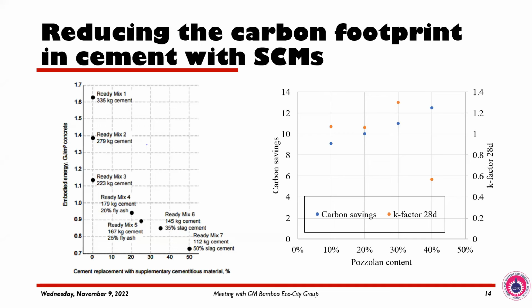So what you do is that you have a score of 1, and then you are replacing the material. If you calculate the efficiency factor of the material you are replacing, and it is below 1, then it means you can't replace cement with the material. But if you replace cement and you have an efficiency factor of above 1, then it means that, yes, the material can replace cement without compromising the properties of cement. It's as simple as that.